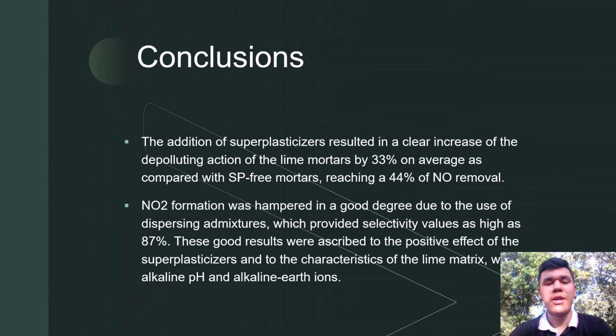Conclusions. The addition of the superplasticizers resulted in a clear increase of the depolluting action of the lime mortars by 33% on average as compared with SP-free mortars, resulting in a 44% nitrogen oxide removal.